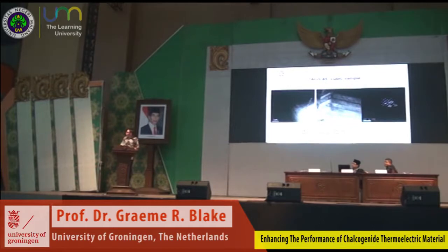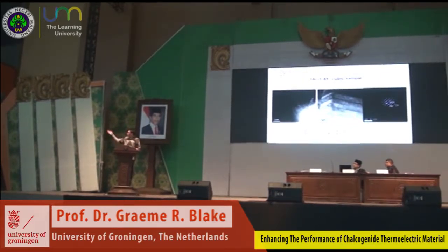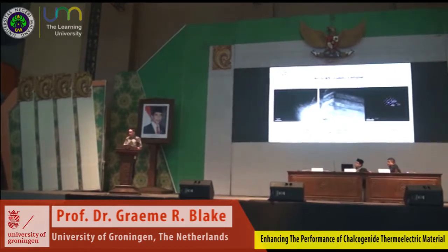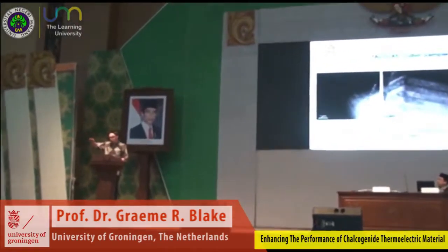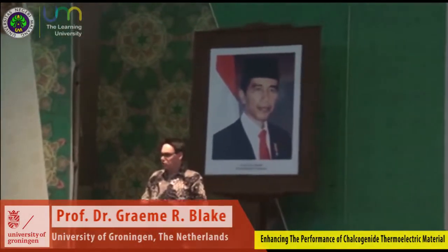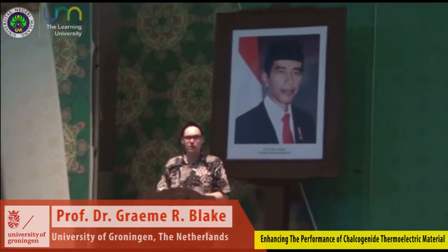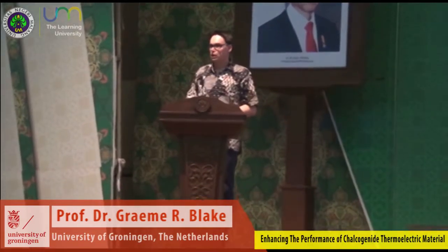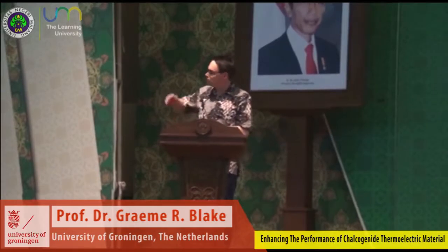This cubic phase at room temperature, although it looks cubic by X-ray diffraction, when you look at electron microscopy images, you still see the zigzag domain structure, which I think is impossible to have in the cubic phase. So this may be a case of X-ray diffraction only showing the broad average structure of the material, whereas on the local length scales it may still be rhombohedral, but this is still a bit of an open question and we need to investigate this further. Next, please.